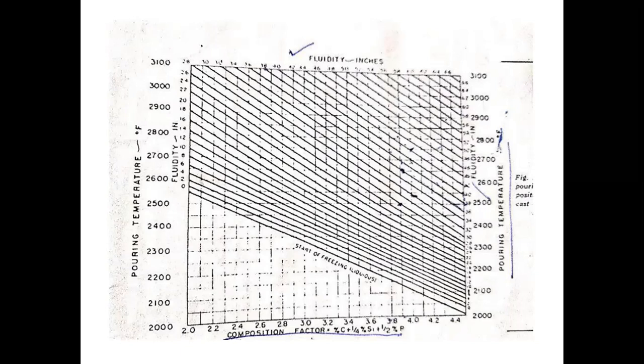But practically, what happens is the ladle will have some metal at the bottom, 10 kg or 15 kg, and if you pour the metal, then more drop will be there. So these are the practical aspects that need to be seen. But at least as per section thickness, if you are going to pour a flywheel or heavy casting, 1350 will be all right. But in case of blocks, heads or tractor housings, which have a general wall of 6 mm, core weight around 70 kg, casting weight around 80 kg, and general height of the casting around 400 mm, total height above parting line 200 to 250 mm.